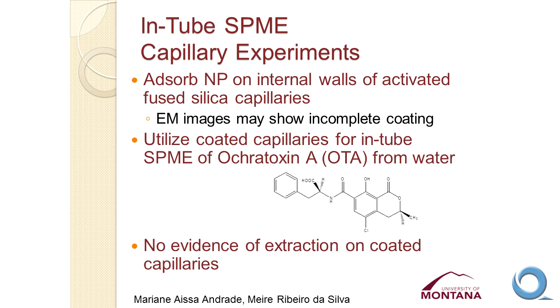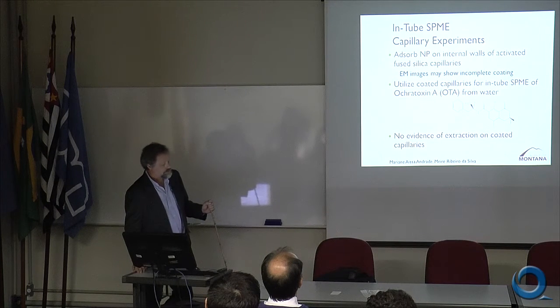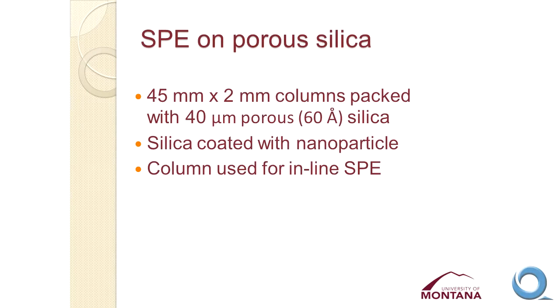And various attempts with various nanoparticles, we really never found any evidence that we were getting a good extraction of the OTA from aqueous matrices. So a little bit discouraging, but probably because we don't really have a thick uniform coating on the surface of the capillary. And so the capacity and the phase ratio in this case is going to be relatively poor.